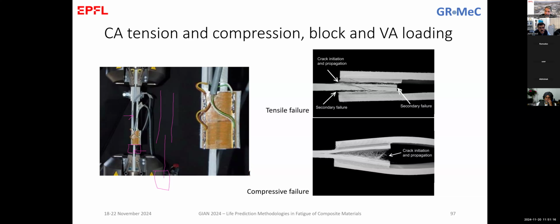So the idea was to see how the joint, so the investigation for us is the joint area. And we wanted to see how the joint behaves in compression. And in compression, you don't have another way to do this test instead of performing a test like that. What we could do, for example, to follow your suggestion, was to make here a very stiff element that doesn't buckle also. And then it would be a pure compression. So what we have here is not a pure compression. I agree with you. But we saw what happens in the joint, because the joint itself is compressed. And when the joint is compressed, we had actually bending moments here because of this opening, and we had this mode 1 that happened. It's not a pure compression. I'm with you on that. Okay, thank you so much.